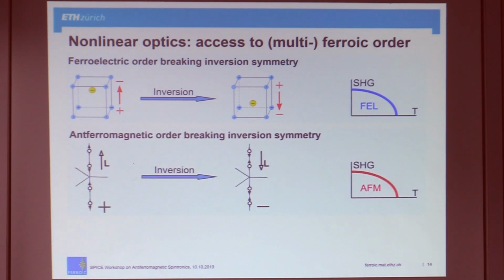This is a big advantage compared to MOKE, for example. And the same works magnetically. So here we have our chromium oxide spin structure. It also breaks inversion symmetry. It gets you from up, down, to down, up, down, up. So right at the Néel temperature, you would get a second harmonic signal. And this is nice because second harmonic generation doesn't care if it's ferro or antiferromagnetic. So you don't need a magnetization. And that's exactly what you need in order to detect antiferromagnetism.